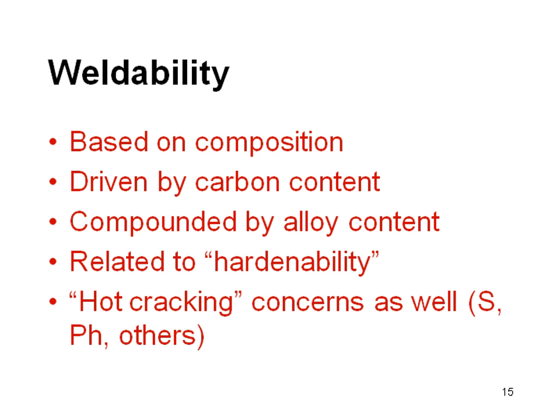And steels with high levels of hardenability are able to achieve high hardnesses very easily. And in welding, we really don't want the steels to get to high hardenability. We prefer steels with lower hardenability. We prefer low carbon steels, low alloy steels for good weldability. So if you will, weldability and hardenability are inversely related.